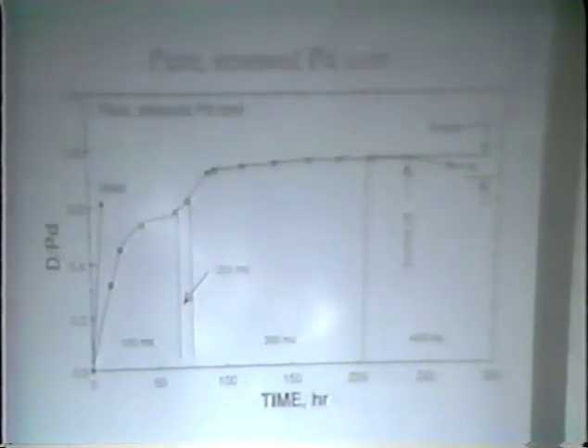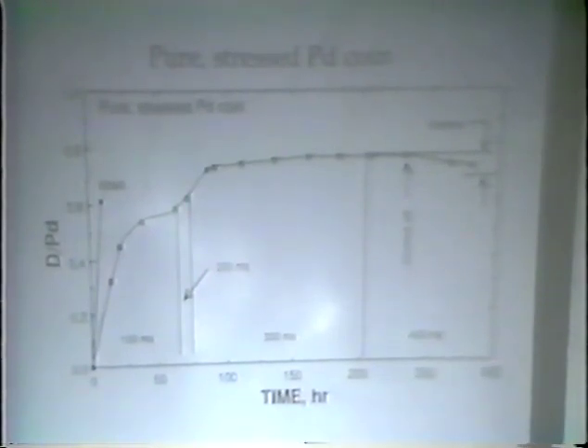We raised the current again. Nothing happened. So we turned the current off, and you can see the slow release of the deuterium as the sample approaches asymptotically the equilibrium value of deuterium in palladium at 1 atmosphere of hydrogen or deuterium at room temperature, which is about 0.67.